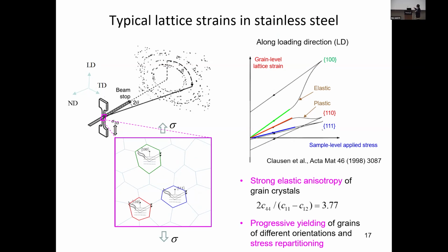The horizontal axis here is the applied load. The y-axis shows the lattice strain of different grain families. When the load is low, we have linear anisotropic responses of different grain families. As the sample enters the plastic yielding regime, we can see different downturn and upturn nonlinear responses. That's because of the progressive yielding of different grain families causing the load shedding and repartitioning among these different grain families. Understanding those dynamics, the progressive yielding and the nonlinear behavior of the lattice strain, enables us to quantify the lattice strains at the grain and the sub-grain scales.